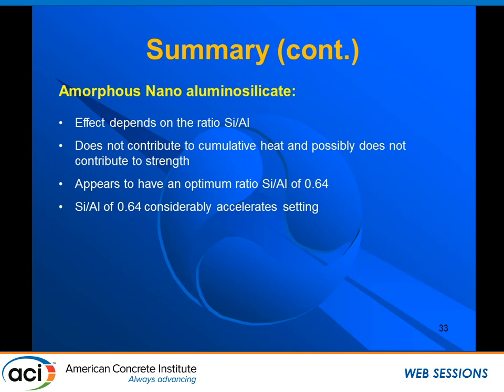And for the aluminum silicate, it appears to have an optimum silica to alumina ratio of 0.64. It helps accelerate setting, but it doesn't seem to contribute to strength. So it forms CSH as well.